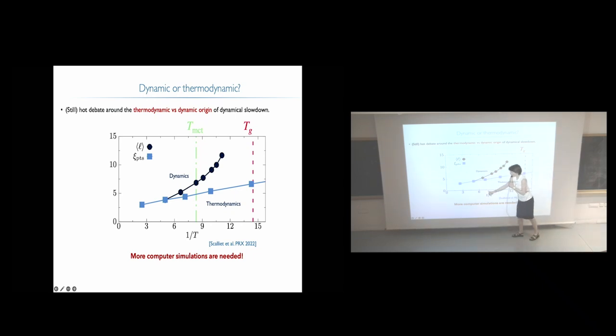So this is thermodynamics, and this is the dynamics. And you see that as you go to lower and lower temperature, the two are getting more and more different. If you imagine that the dynamics is becoming slow because this length scale is increasing, then it seems the dynamic length scale has something more to it than just that. So it is still an open question. There's a lot of debate as to whether this thermodynamic length increasing drives the relaxation, or if there's something more, and Misaki will discuss other ingredients that might happen.